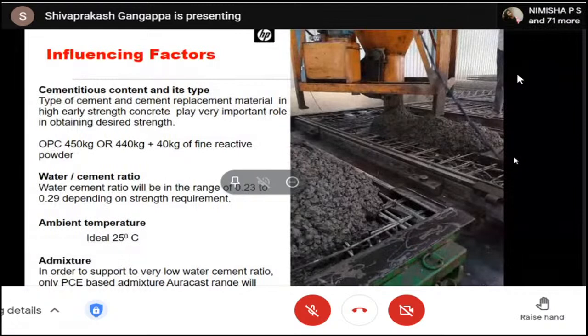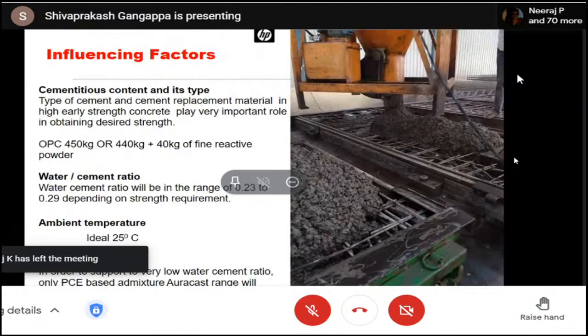So probably the replacement we cannot go more than 10%. If you go anything beyond 10%, the concrete becomes too sticky. Then the shrinkage values will be more. There are a lot of disadvantages. Even as per the standard, we cannot go beyond 10%. But what is practically used is about 8% or 9%. So how can we